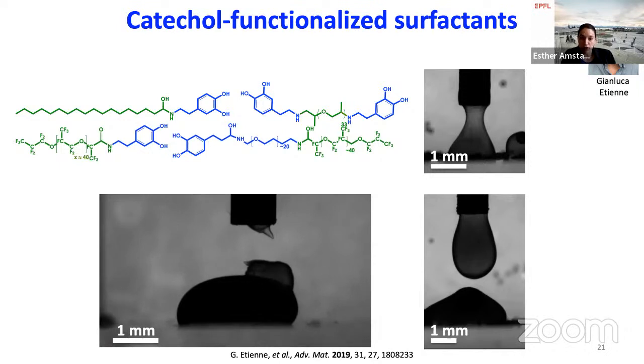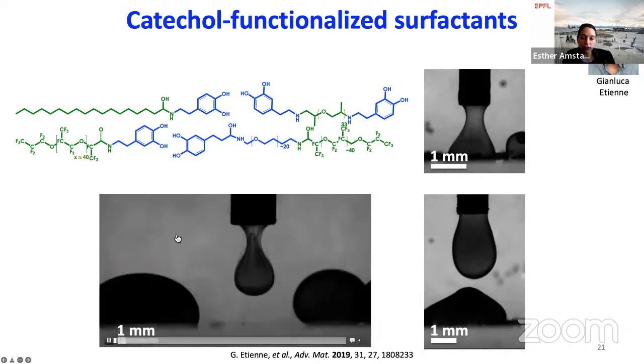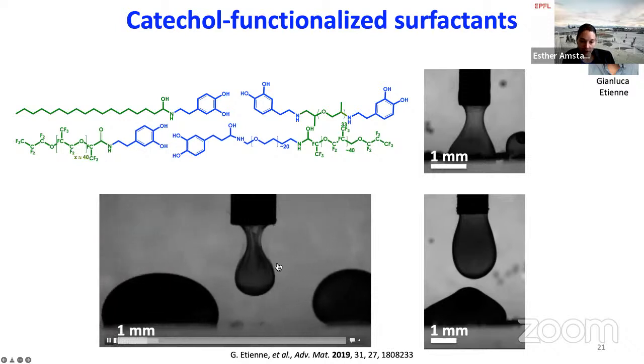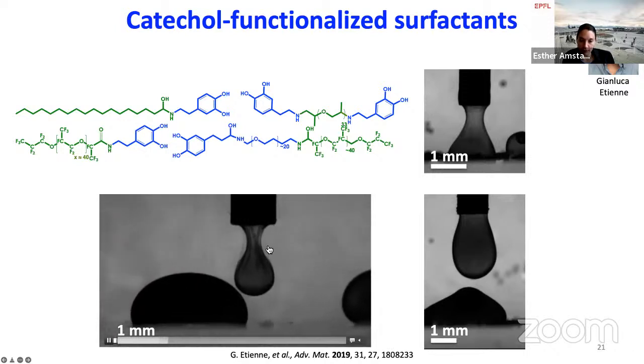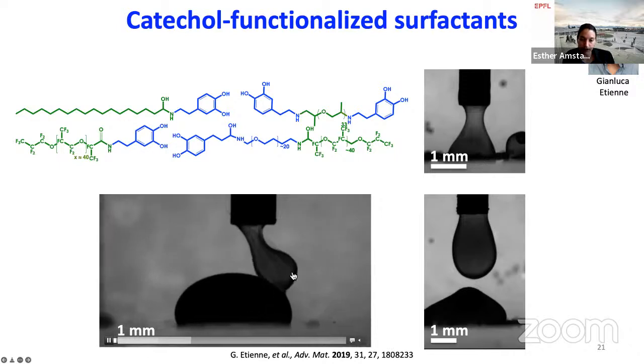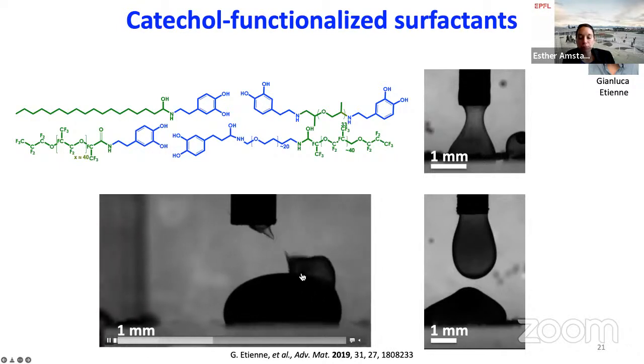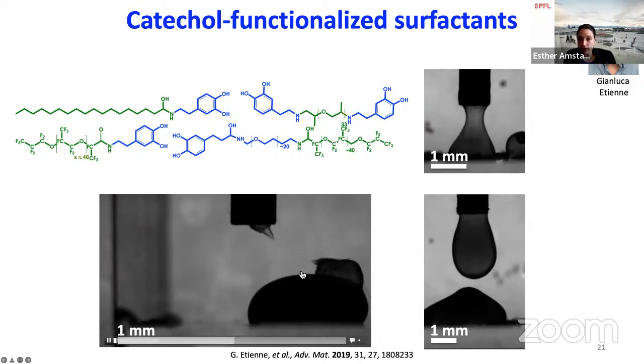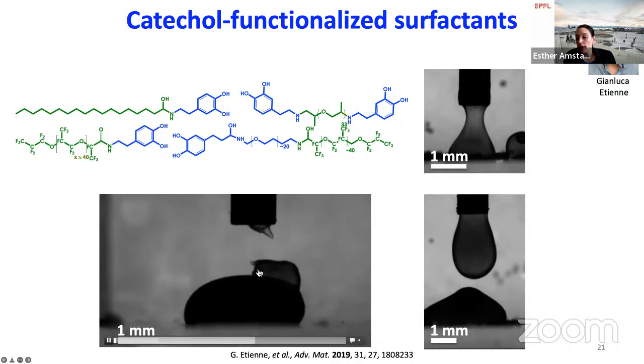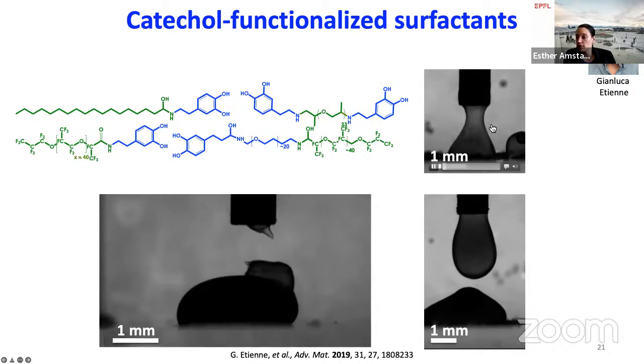and looked at how this ionic cross-linking of the shell influences its mechanical properties. And as you can see here in this movie, you form shells. I don't know if you can see it, but you see a very thin shell that wrinkles here at the drop. And if you put the two drops in contact, you actually see that the two shells merge and you get a fluid exchange, which indicates that these shells are viscoelastic. This you can also see on this movie, that you have something solid, viscoelastic, that you see forming.